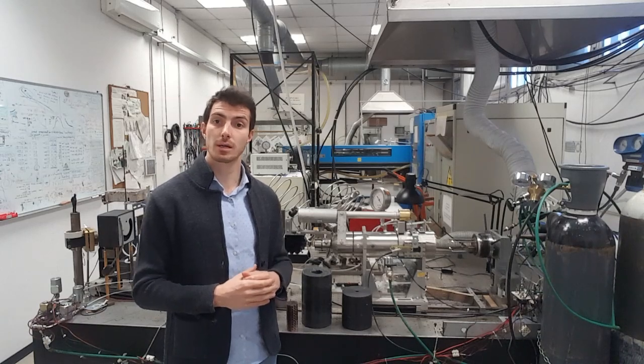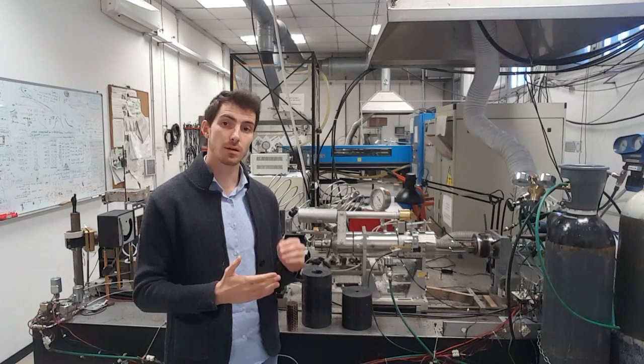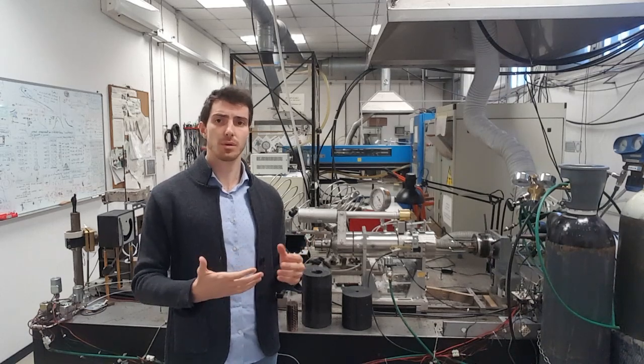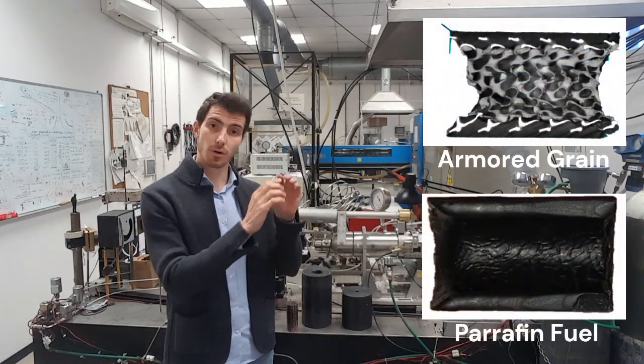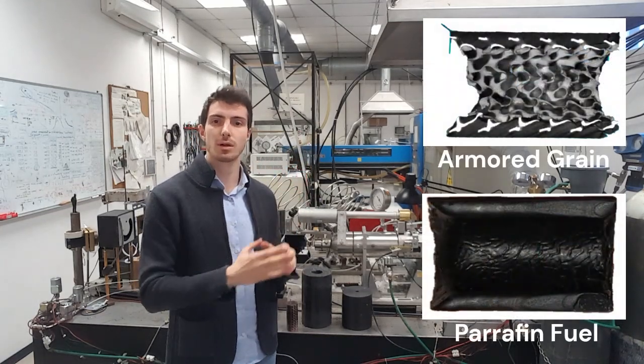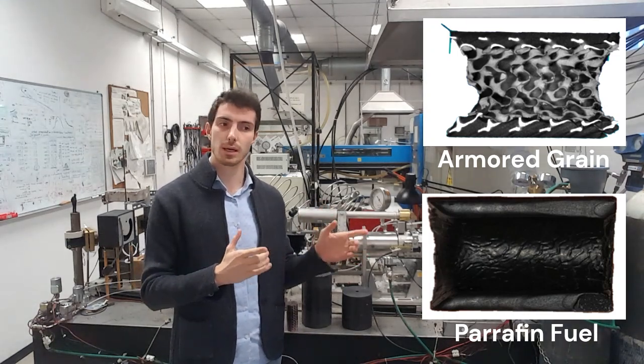The firings attested the excellent ballistic performance of armor grains, even higher than paraffin waxes. This can be explained by the burning surface of the fuel after the firing. The armor grain exhibits a very rough burning surface due to the inner reinforcement that promotes turbulence and boosts the combustion.